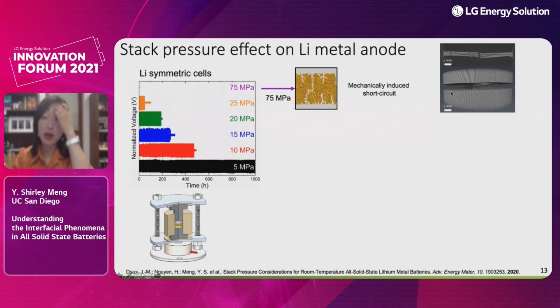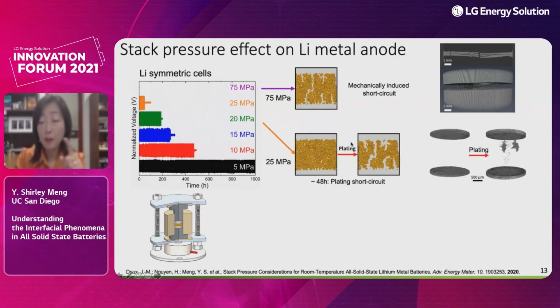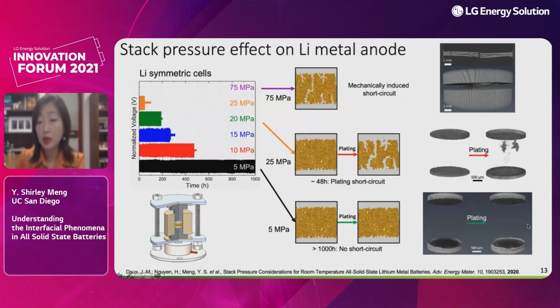So with the micro CT that we have, we were able to look at mechanically induced short circuits. And when the pressure gets lowered, the plating of the lithium metal can be eliminated. So that gives us some very good directions to think about lithium metal anode—perhaps the very high stack pressure is not needed.